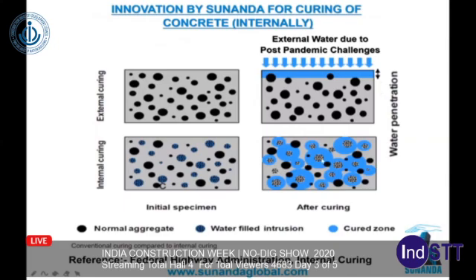Then here we can see what happens whenever we use an internal concrete admixture, as I am showing underneath the classical curing. If you try to do classical curing like water curing over here, then obviously because of shortage of manpower and other things, the curing will not happen, and the depth of concrete curing will also be much less, as you can see here. However, if an internal curing polymer is mixed throughout the concrete, it will get dispersed throughout the concrete. This polymer has a special water absorption capacity, and when dispersed throughout the concrete, it will go on releasing water for hydration, and the concrete hydration will be more towards perfection.